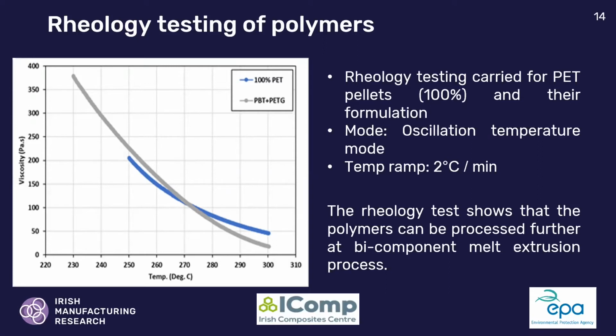The testing mode is oscillation temperature mode. The temperature ramp used is 2 degrees Celsius per minute. For the core, the temperature range is 250 to 300, and for the sheath, 230 to 300.